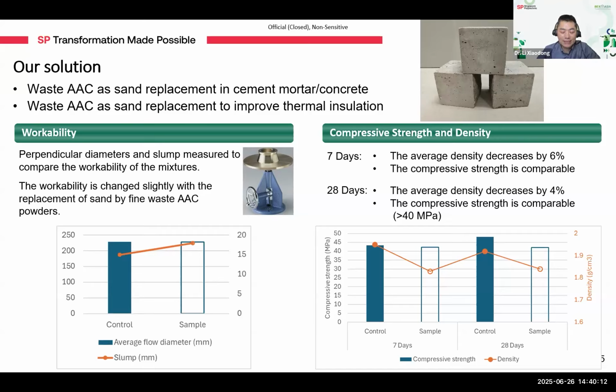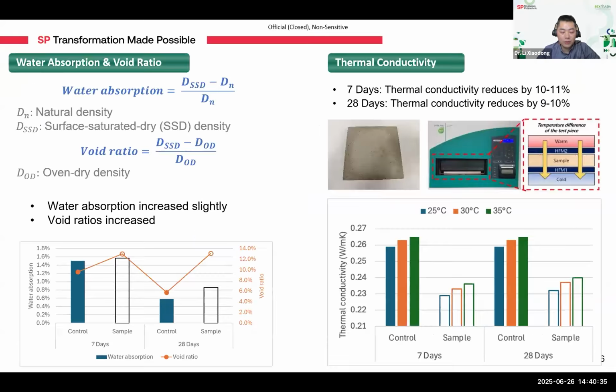So we found the density decreased by about 6% at 7 days and 4% at 28 days, respectively, due to the inclusion of the lightweight AAC powder. And despite that, the compressive strength remained high, exceeding 40 megapascals, which is comparable to the control mix made with the natural sand. We also analyzed the material's water absorption and void ratio, given the use of the porous material.